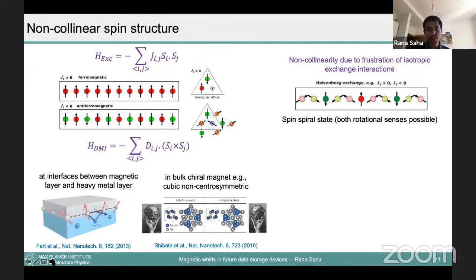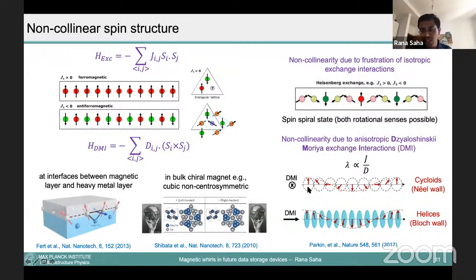What do I mean by chiral? Like your left hand and right hand. If you have a spin structure with non-superimposable mirror images, those are potentially very useful structures for this racetrack application. When you have a non-collinear magnetic interaction, called the Dzyaloshinskii-Moriya interaction, you can have a structure where spins go in a helical motion, in a counterclockwise or right-handed or left-handed fashion.